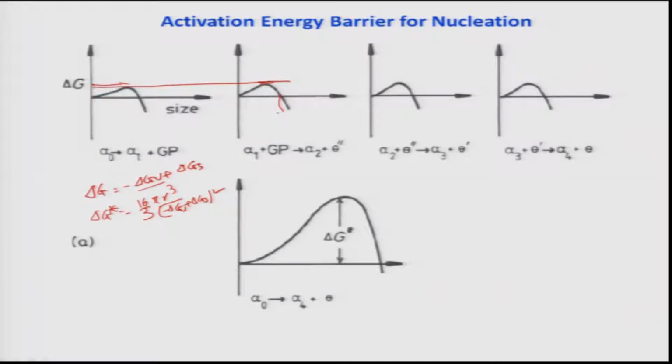That is obvious because again theta double prime is coherent. The only thing which normally can change is the strain energy, which is a little higher because of the presence of the copper atoms, more specifically they are present in the crystal. But on the other hand, if you look at theta prime and theta, the activation energy is very high, and slowly it is increasing, stepwise.